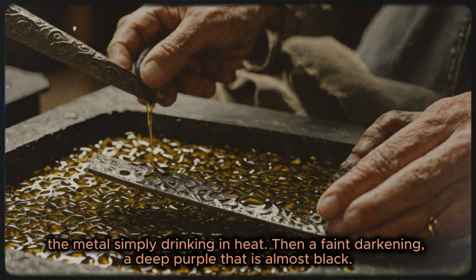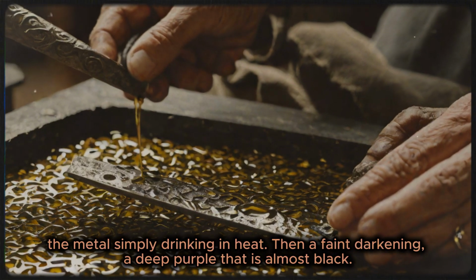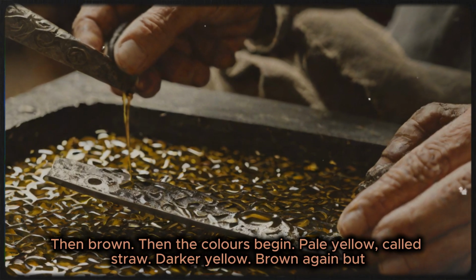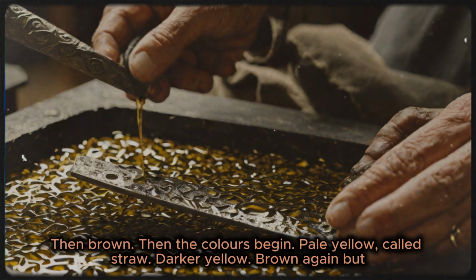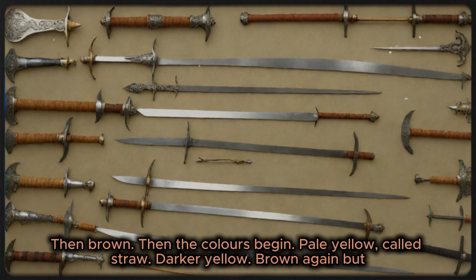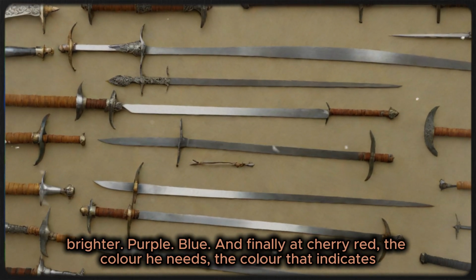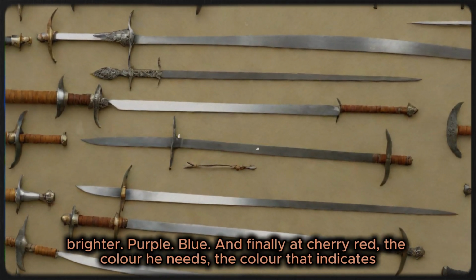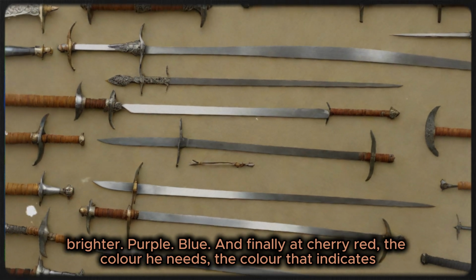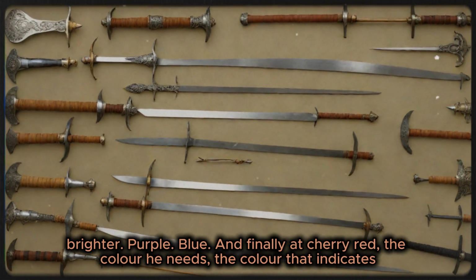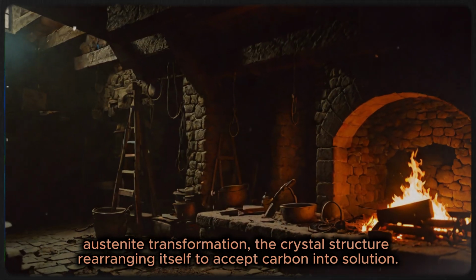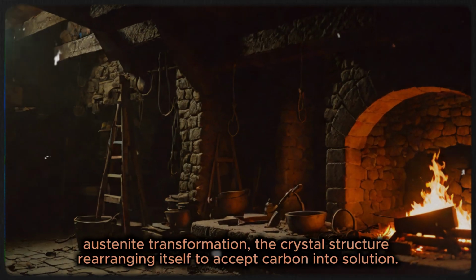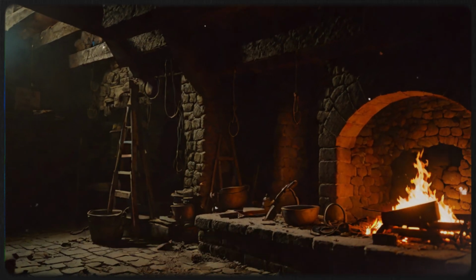Then a faint darkening, a deep purple that is almost black. Then brown. Then the colors begin. Pale yellow, called straw, darker yellow. Brown again, but brighter, purple, blue. And finally, at cherry red, the color he needs, the color that indicates austenite transformation, the crystal structure rearranging itself to accept carbon into solution.